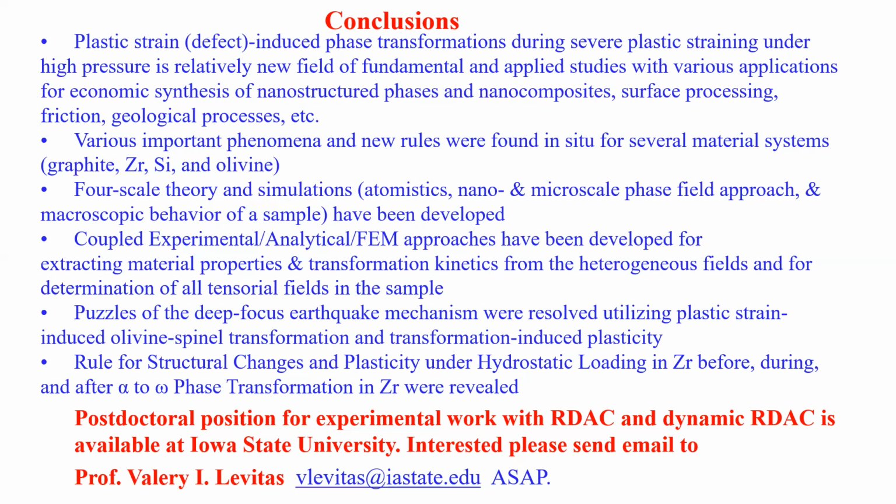So all that you said is exactly true, and that is what we take into account by multi-scale modeling. When I said reduction in pressure, that is the average pressure applied to a material point of the size of several micrometers. But within this micrometer, indeed, stresses in some regions can be much higher. In others, they are lower, but the average is like this. Very good point, and exactly what I wanted to say.